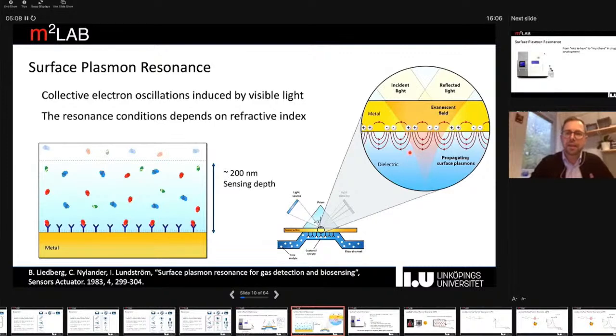These propagating surface plasmons are essentially collective electron oscillations that are induced by visible light, and which essentially result in an evanescent field that propagates into the surrounding medium. That's what's tried to be illustrated here. And that evanescent wave essentially reaches out roughly 200 nanometers from the surface into the surrounding medium, which makes this a fairly surface sensitive technique. So we can monitor what goes on close to the surface here.